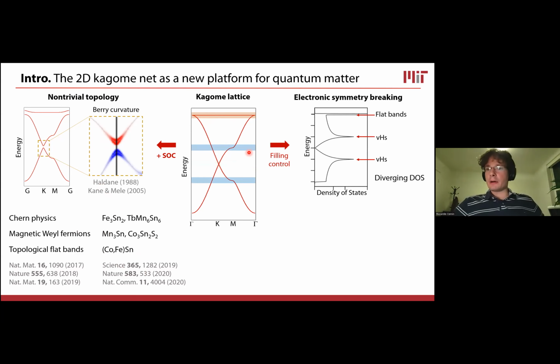If you now play with the chemical potential and shift it close to the Van Hove singularities, or the flat band, now you're in a different limit where the phenomena you can realize are enabled by having a large density of states at the Fermi energy, and the system typically doesn't like that. So it wants to remove that degeneracy by breaking symmetries.